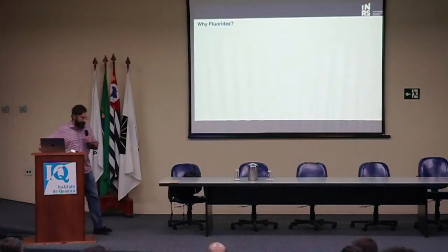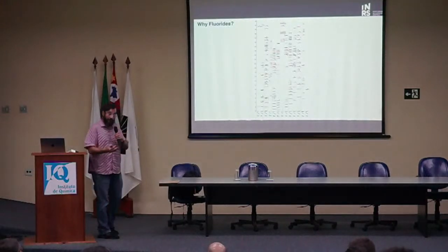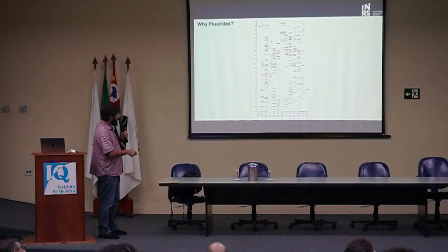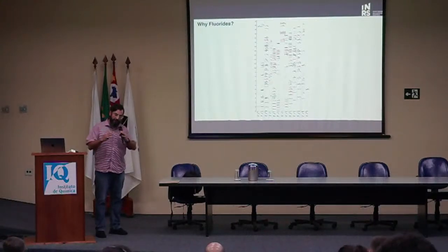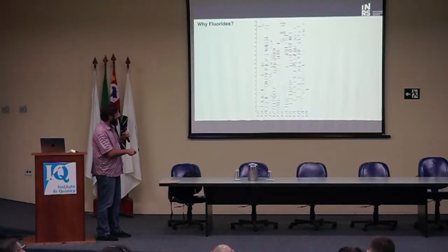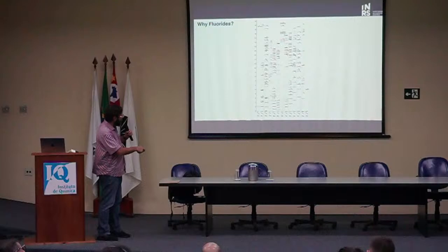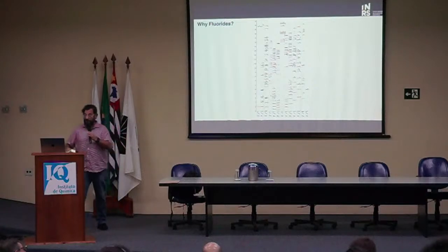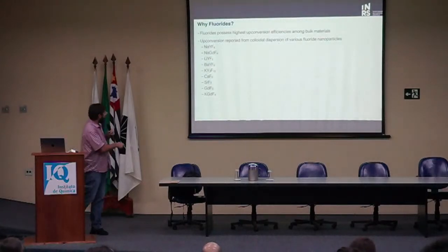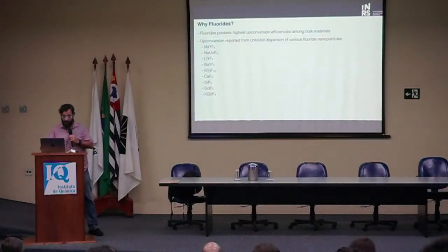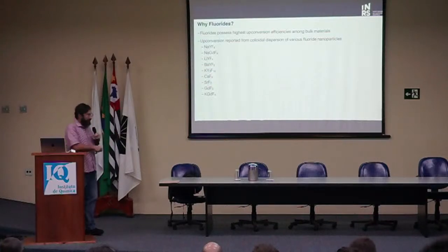Now, why fluorides? Again, if we go back to the Dieke diagram, I point to the plethora of these 4f electronic energy states, which means that the upconversion, and most of the luminescence, is very sensitive to the lattice vibration, to the phonon energy of the material. If the phonon energy is too high, once the ion is excited to the intermediate state, the ion will non-radiatively decay down to a lower state. Now, if you look at upconversion, you see that there is no state above with a similar energy gap. And so that significantly decreases the intensity of the upconversion, okay? And all the other luminescence as well. So we need materials that have low phonon energies, and at the moment the fluorides are pretty much some of the state of the art. And we worked with most of these in one form or another over the years.